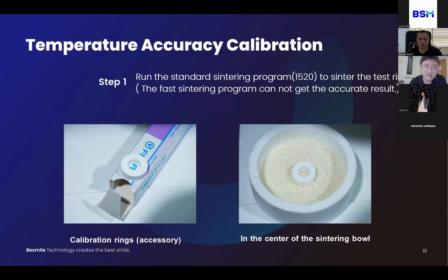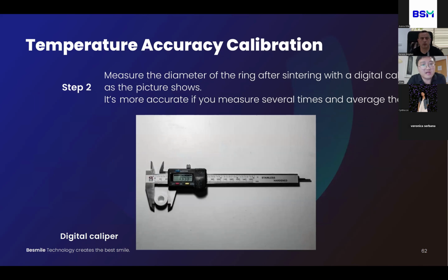Step 1, we need to run the standard sintering program to sinter the test ring. We cannot use the fast sintering program because it cannot get an accurate result. After sintering, we need to measure the diameter of the ring with a digital caliper, as this picture shows. We can rotate the ring to measure it in different directions to get several measurement results and get the average value.